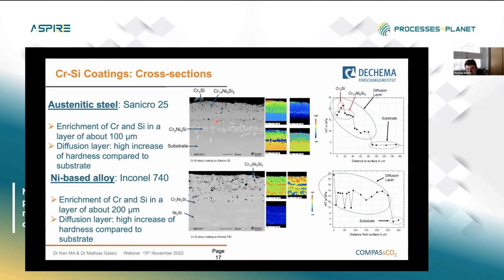And as you can see on the right side, we find a chromium-rich phase without many cracks. We have a few pores, mainly those round shaped pores, which are internal silicon oxidation during the process. But in general, we have very high hardness, as you can see on the right, and also, what we expect, a highly improved oxidation resistance.